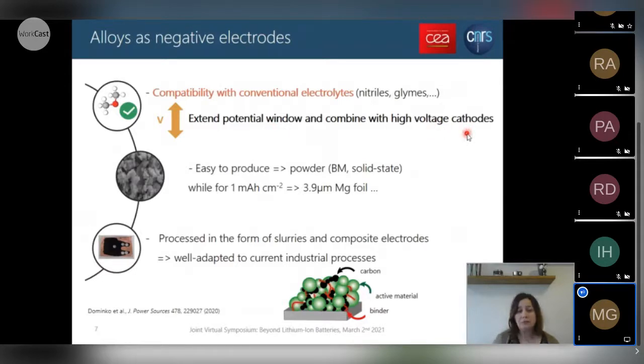a high voltage cathode. Second, these alloys are maybe easier to produce than magnesium metal. We can produce them in the form of powder through, for example, ball milling or solid state synthesis. While if you think about a magnesium metal foil, for example, for a surface capacity of 1 milliampere hour per centimeter square, even if you consider an excess of 50% of magnesium, you need to produce a magnesium foil of around 4 micrometers, which may prove difficult to produce in a really clean way. And finally, the last advantage is, as we have powders, this can be processed in the form of slurries and composite electrodes with similar industrial processes that are currently being used in the lithium battery industry.